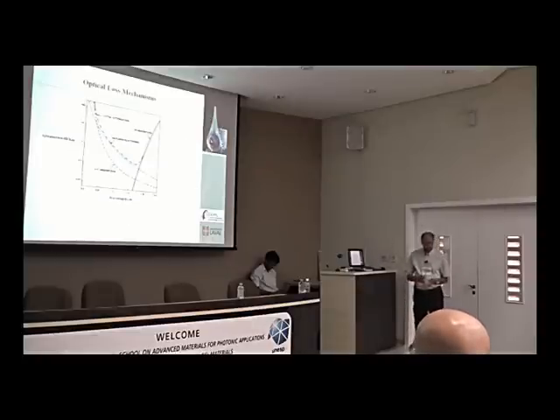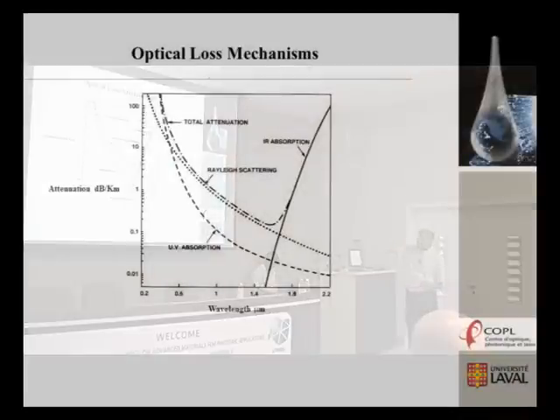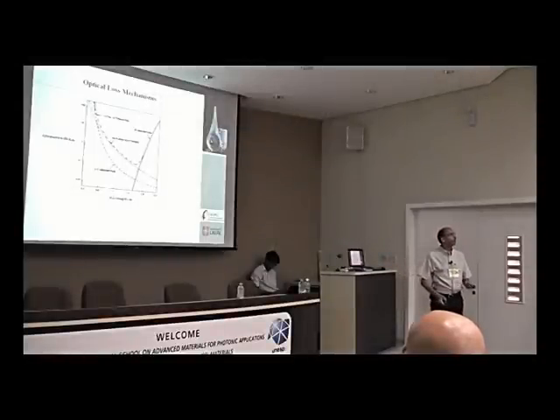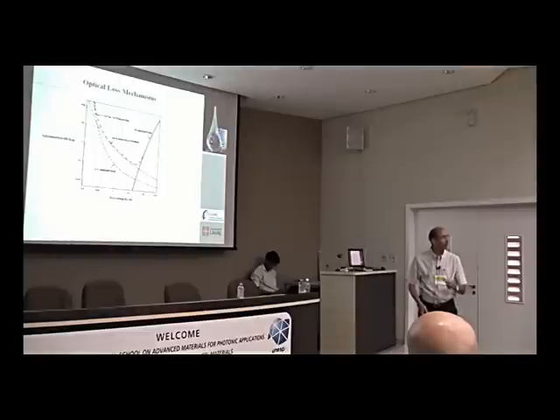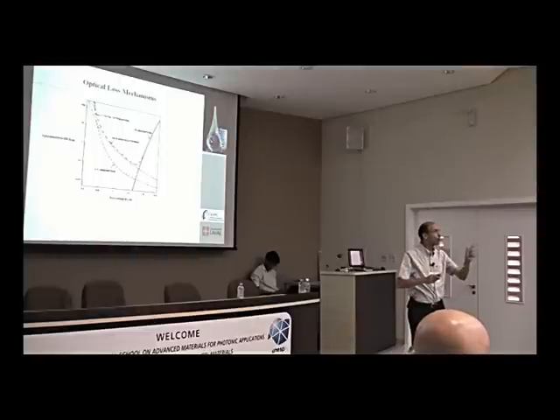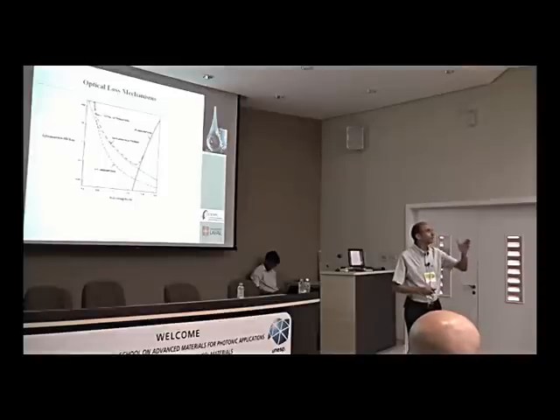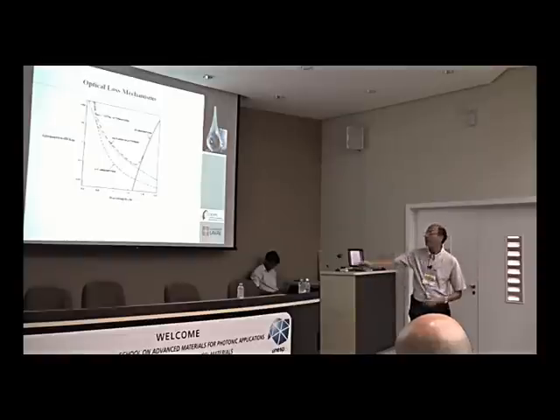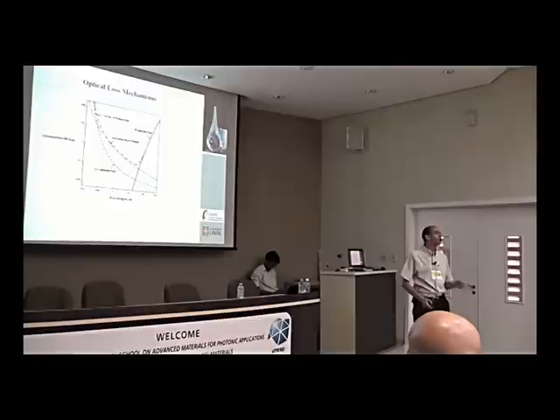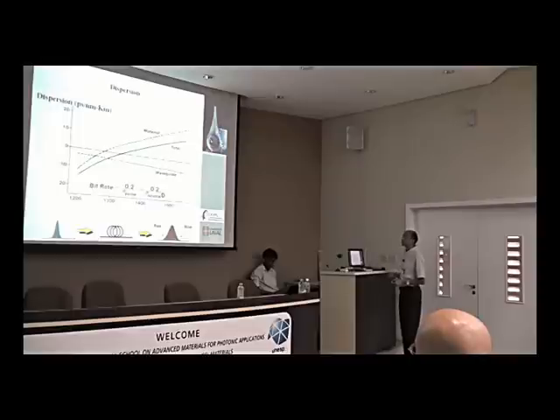And this is the behavior of optical losses that I saw in the beginning, that I explained in the curve, the attenuation versus wavelength, and we have all these parameters. The total one, which comes from UV plus infrared and Rayleigh scattering, all together give us this total curve, and this gives us the minimum of the losses at a specific wavelength. And typically for silica fiber, it's around 1.55, what we call in the telecommunication world the C-band, the central band. Why the central band all the time? Why 1.55? Because at 1.55 we have the lowest losses, we reach 0.2 dB per kilometer. This is the answer to the question.